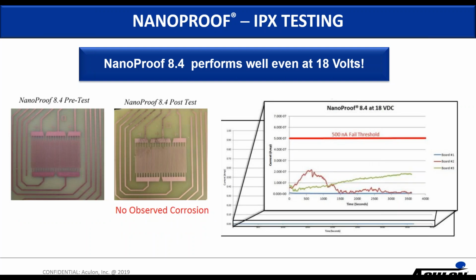And then 8.4, again, there's no observed corrosion. You may observe in the picture that there's some markings at the top. That's just a blemish on the part. That's not where you would actually see the corrosion taking place. And again, the 8.4 is well below the 500 nanoamp spike threshold. You can see there's one part that had a rise up to 200 nanoamps of current, and then another that had measured a slow approach to almost 200 nanoamps as well. But all three test boards are well below the 500 nanoamp failure threshold.